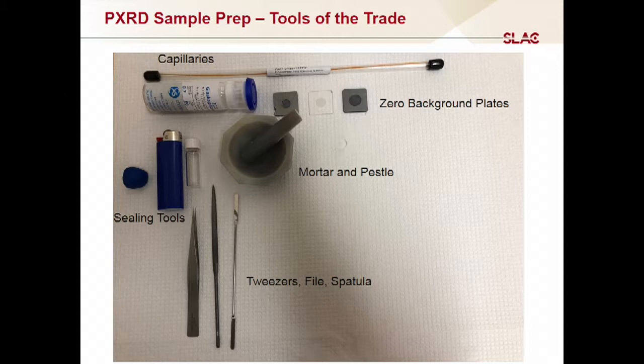These are a polymer capillary. You tend to buy them in long lengths and cut them down to size. The glass ones are nice because they have a large funnel on one end that makes it easier to get powder into it to start the whole process. The Kapton ones don't have that, and so scooping up powder with those very thin capillaries can be a little trickier, but you can do it. The other thing that you may do, if you don't want to measure it in a capillary geometry for whatever reason, is measure it in a flat plate geometry.